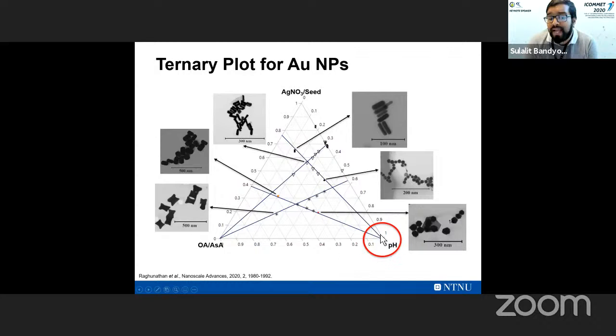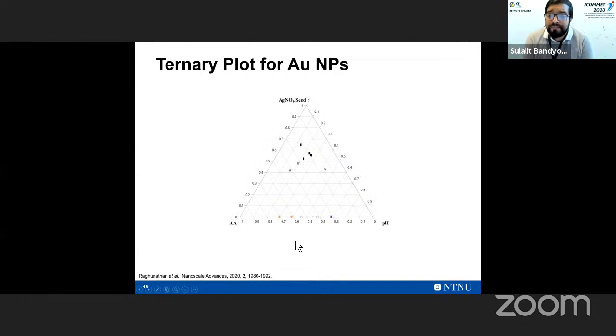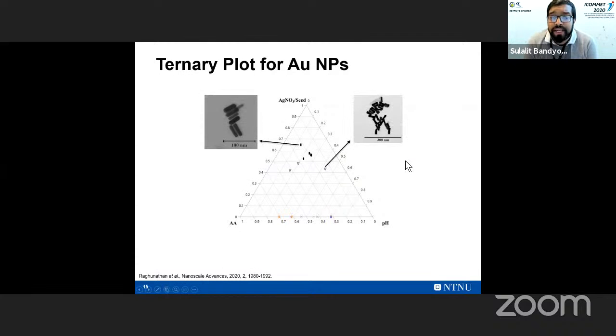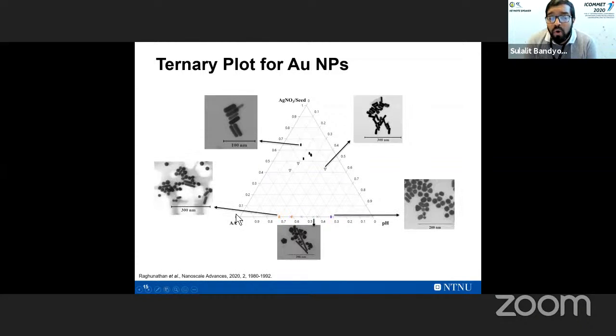Now, what we can't see on this phase diagram, if some of you are observing, is the vertex around this pH, because there are several points clustered together. So we split them up, and then we see in pH that we remove the oleic acid. So this is for no oleic acid systems. And what we can see is that if we go in different directions of the pH, keeping the other factors constant, we can go from a very bad distribution of particles to a nicer distribution. So the pH is a very important factor in this regard.